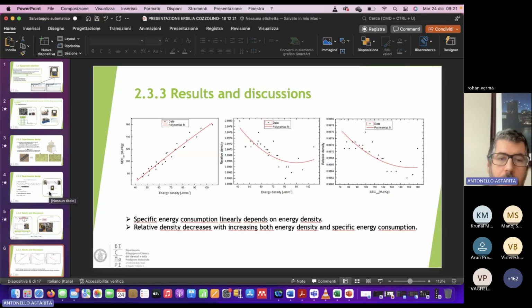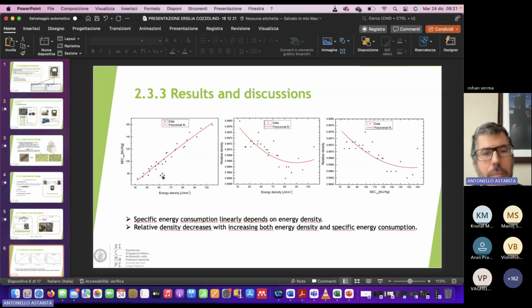At the end, we found a direct link between the specific energy consumption in additive manufacturing and the energy density. As you can see, this is an unexpected result. By increasing the energy density, you increase the specific